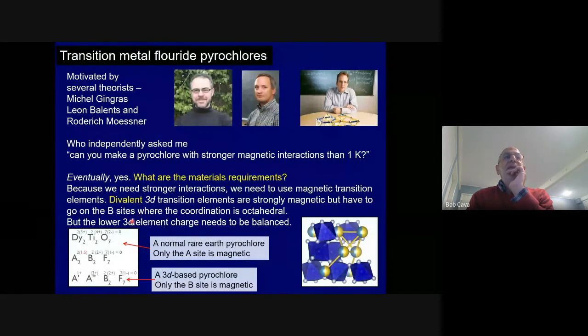But there's a problem with that. There are two problems with it. First of all, we have to put them on the B site in the pyrochlore, which we realize is also geometrically frustrated. And so we have to have non-magnetic atoms on the A site. We have to have divalent atoms on the B site. And we have to have the right amount of charge so that they become charge balanced. So you therefore have to make these things with fluorides, not oxides. So we were able to figure out that by making A'B2F7, we can make rare earth pyrochlores that were magnetic and had a higher interaction temperature.